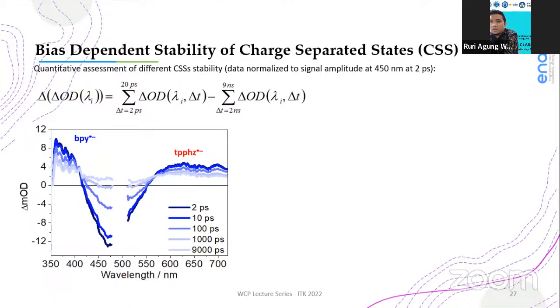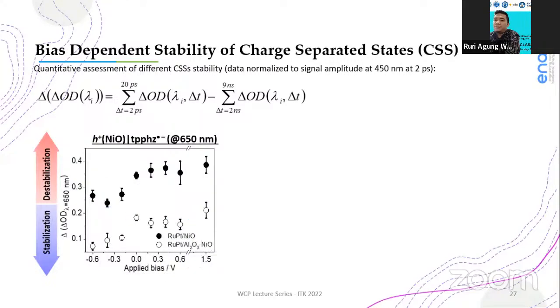And then we want to get a quantitative value of the charge separated state stability. So we make another delta OD, difference absorption, which is calculated as follows. The delta OD is the subtraction between the signals at short delay times, which corresponds to the initially formed charge separated states, and the signals at the longest delay time, which indicates the remaining charge separated states within our experimental window. So here, smaller delta OD means more stable charge separated states, while higher delta OD indicates destabilization of charge separated states. The result shows that at positive bias, the delta OD signals increase, indicating the destabilization of both charge separated states.